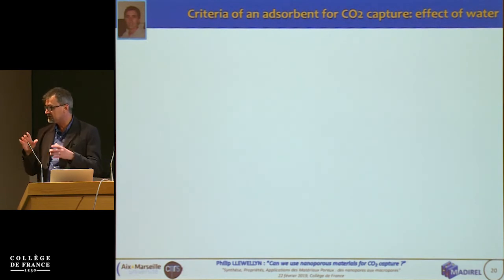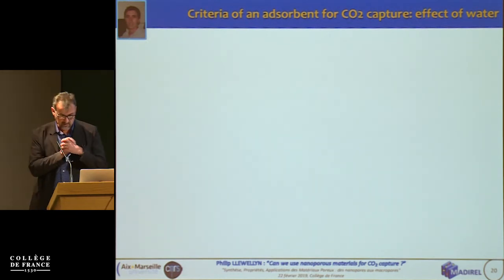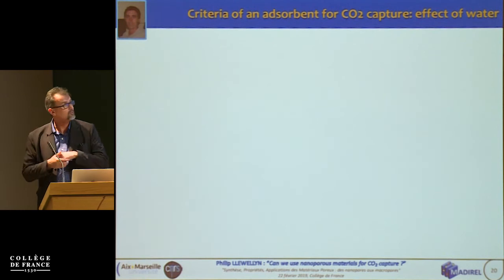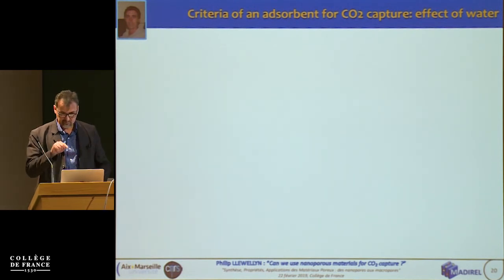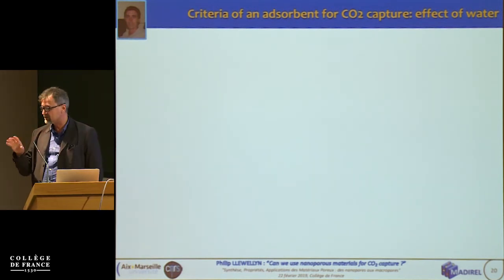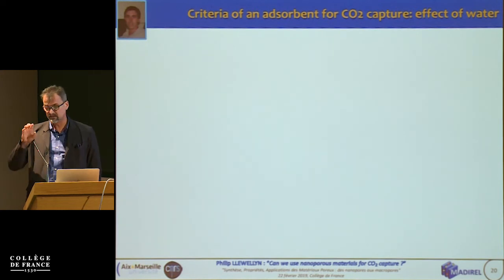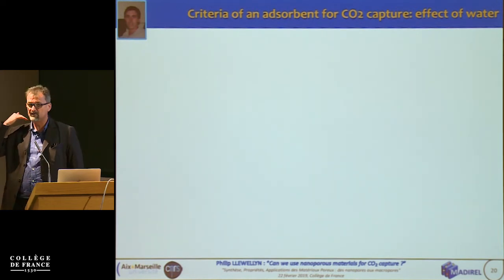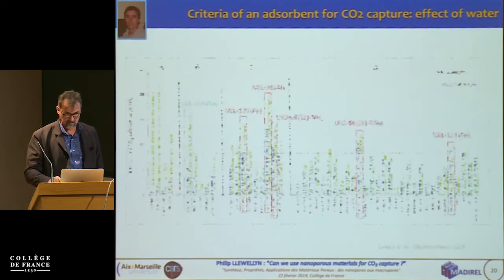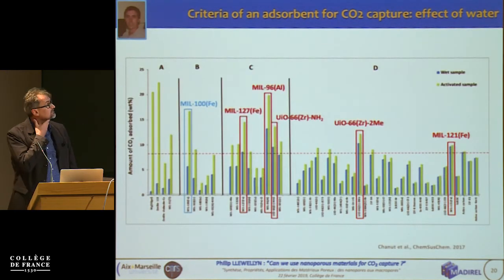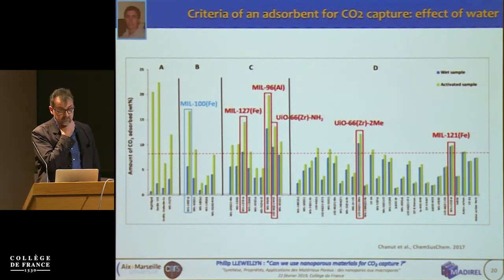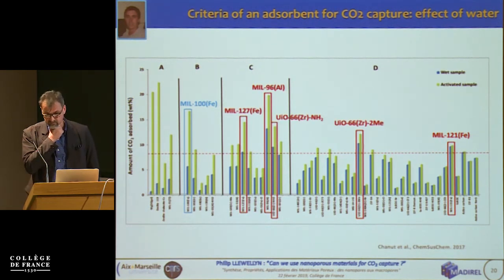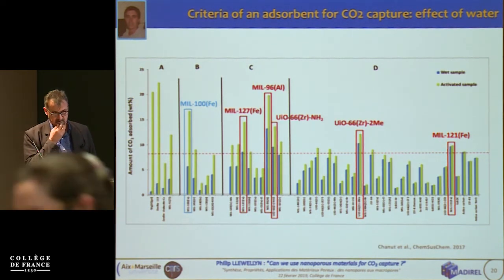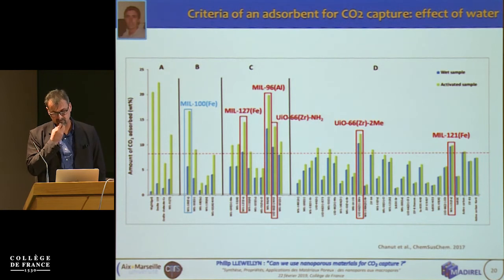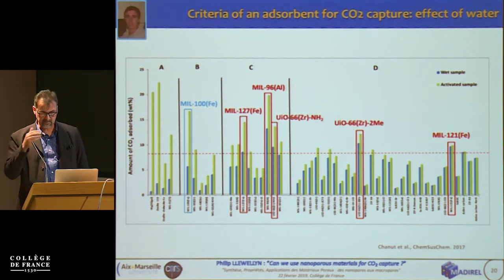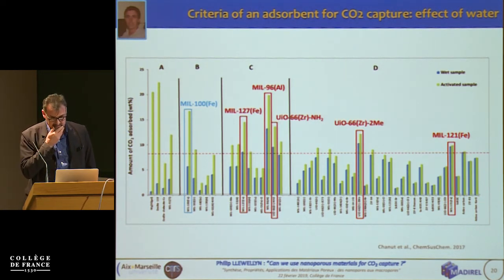So we've picked out a material. We found that it has good working capacities or whatever. The first problem after that is someone's going to say, okay, in my process I have contaminants, and the flue gas is wet. There's water in there. So what we've done is set up a really simple system in that we've looked at the CO2 uptake at 0.2 bar, so a little bit below atmospheric, the sort of pressure range that would be used in applications, in a wet system and in a dry system.